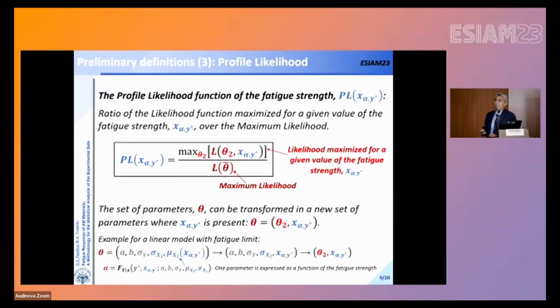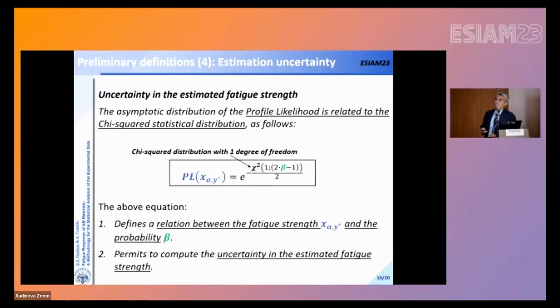Here, there's an example of the procedure that you can follow to transform, as an example, the mean fatigue limit into a function of the fatigue strength. So one of the parameters is transformed to get the fatigue strength inside. At the end, the most important aspect is that you will have a function that depends on the fatigue strength. And this is quite important since it can be shown that the probability distribution related to the profile likelihood function is a chi-square distribution. And so the profile likelihood, which depends on the fatigue strength, can be correlated to a probability.